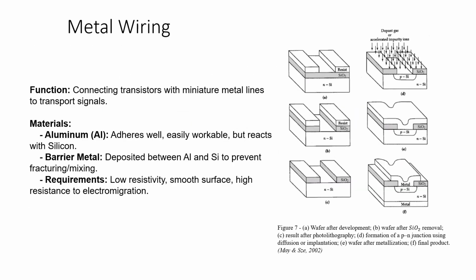And the next part is metal wiring. To connect the transistors, we use metal wiring. Aluminum is commonly used for these interconnections because it adheres well to the oxide layers. However, aluminum and silicon tend to mix at junctions, which can cause fracturing. To prevent this, we deposit a barrier metal between them to ensure the reliability of the junctions.